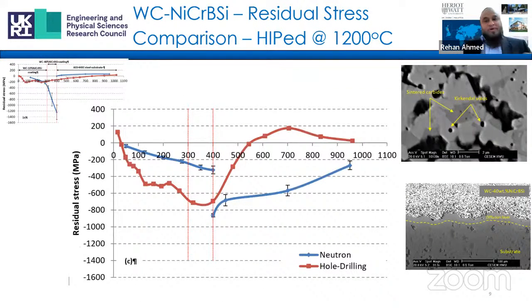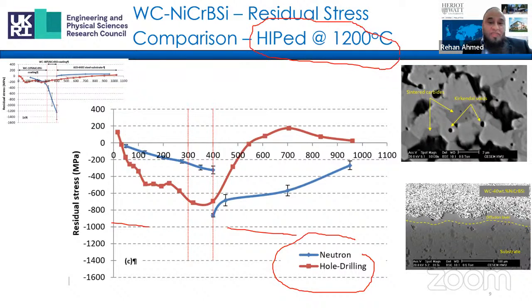So this slide provides the comparison of the same coating, which I showed in my last slide of the bilayer system. And it shows the changes in the residual stress profile through thickness in the coating and the substrate system after it has been heat treated at 1200 degrees Celsius. And the changes in this particular case are linked to the sintering of the carbide as shown in the SEM, and also the formation of a diffusion layer near the coating substrate interface.